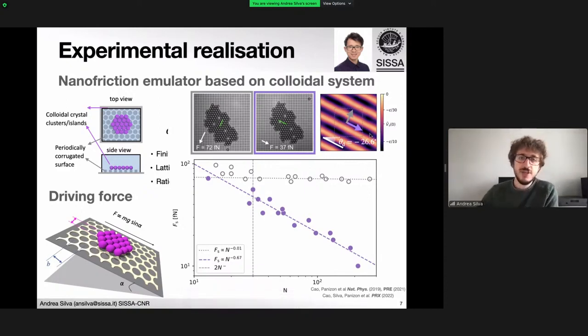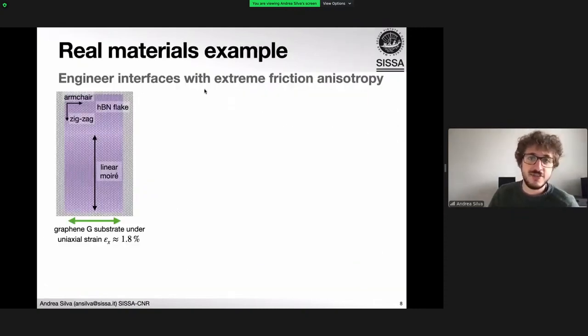So one last thing that we can do is reverse engineer this process and design an interface with an extreme friction anisotropy. In this case, we took a graphene substrate and we uniaxially strained it along X by about 1.8%, which is well within experimental values. And then we place an hBN flake on top of it. And we can go and see what happens as the size of the flake increases.